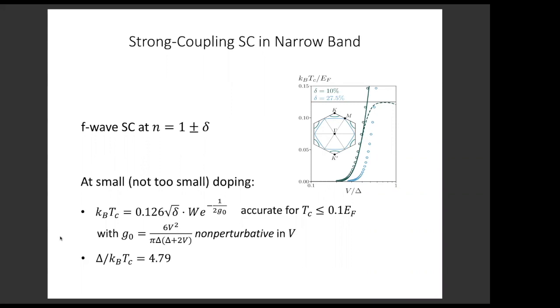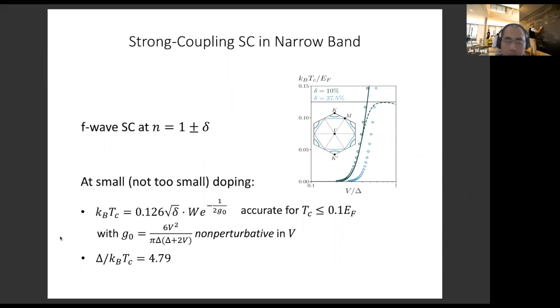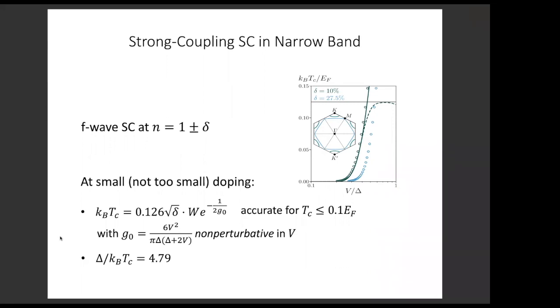So as you increase the interaction strength, the coupling constant G0 increases and the Tc increases with it. And this formula that I'm showing here is quantitatively accurate even when Tc reaches 10% of the Fermi temperature. So that's a very strong coupling superconducting state. Moreover, the ratio of the superconducting gap and Tc is 4.79. It's much higher than the BCS value, which is 1.75. Okay, so let me now describe how these results are obtained.